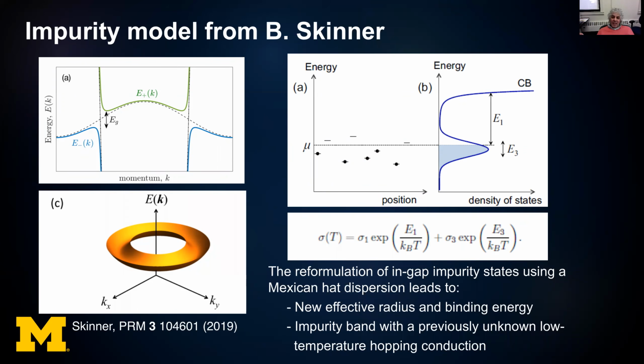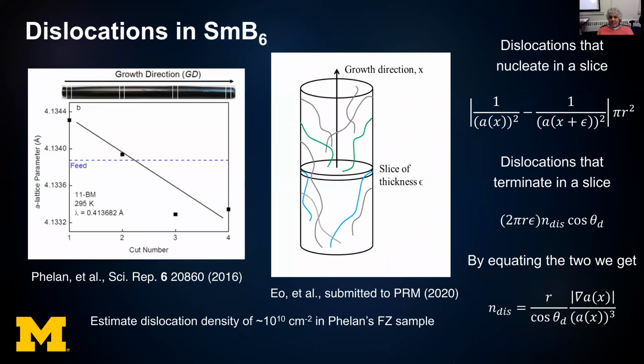One is, of course, hydrogenic impurities, which we first thought wouldn't be present, but there is a recent work by Brian Skinner suggesting that when you use the Mexican hat dispersion, then you would get hydrogenic levels with low binding energies and a new kind of impurity conduction, which we are hoping to investigate. And the other thing that we particularly worry about is transport through dislocations. We know dislocations must be present.